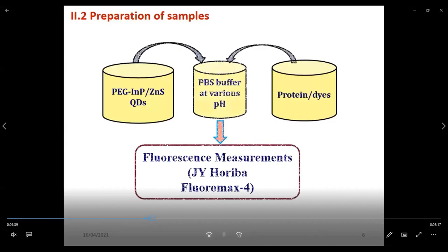For the preparation of the samples, first I have taken HSA and BSA in two different PBS buffer solutions which are at various pH values, and QDs which are also at various pH values. Now they are mixed to form the bioconjugates. And such samples were further used for recording the fluorescence spectra with the help of the Fluoromax-4 spectrofluorometer.